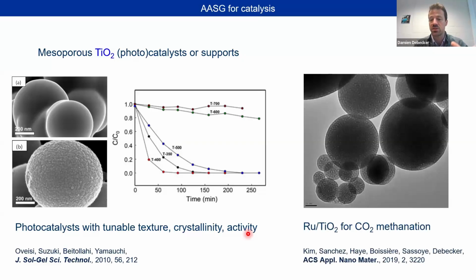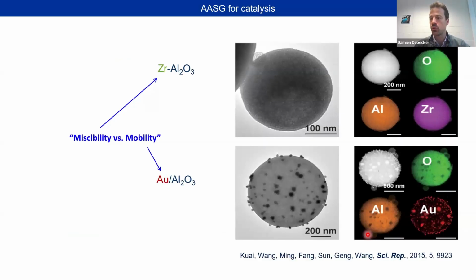We have also used, for example, these kind of materials as support for ruthenium and exploit them in CO2 methanation reaction, for example. You can also find in the literature examples with alumina, ceria, zirconia, etc. I like this example here because these authors have prepared an alumina and then they have blended from the starting solution the precursors for alumina with a precursor of zirconia or gold. And in this illustration, I think it's really nice because it illustrates two scenarios. The first one, I call it the miscibility scenario.